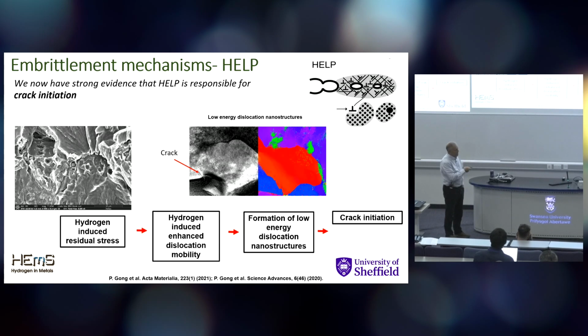So the sequence we think happens here is that hydrogen induces residual stresses within the material, certainly introduces the high dislocation density. But the other thing which I haven't mentioned is that the atomic modelling suggests that the mobility of dislocations in steel is much higher in the presence of hydrogen, and that's been confirmed experimentally. So we not only have a higher dislocation density, they are also more mobile. So we think those come together to form these low energy dislocation nanostructures, and that leads to the crack initiation, which you can see here.